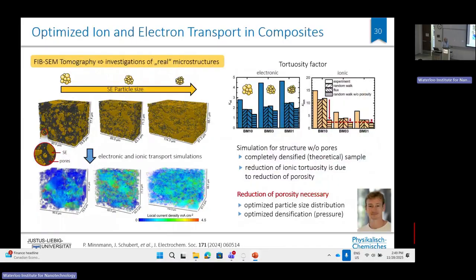Well, today, we and others did that, of course, a bit more professionally, by digitizing or making digital twins of real composite electrodes, and then making digital analysis of the paths. And what we found out is that always in practice, so this is, in fact, the tortuosity factor, which is a measure of the difficulty of your path. The more tortuous your path is, the more curved it is, so the more difficult it is for your charge carriers to go through the electrode. So the higher, the worse.